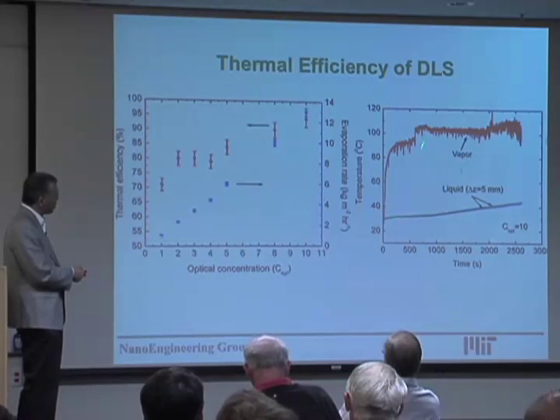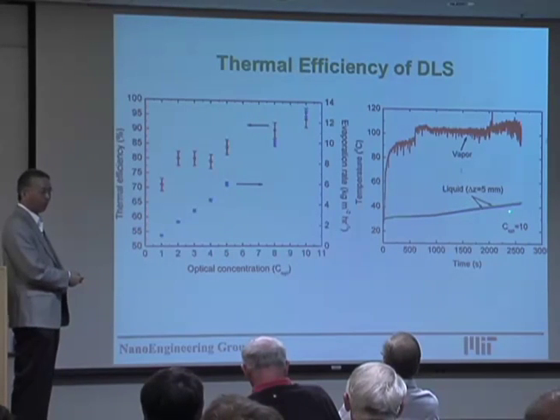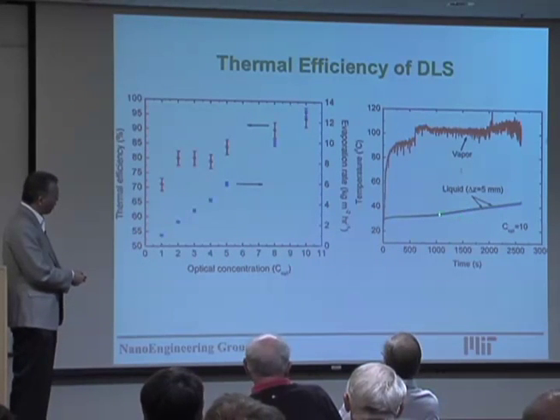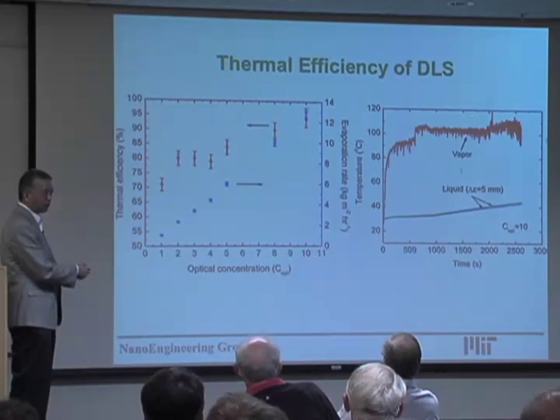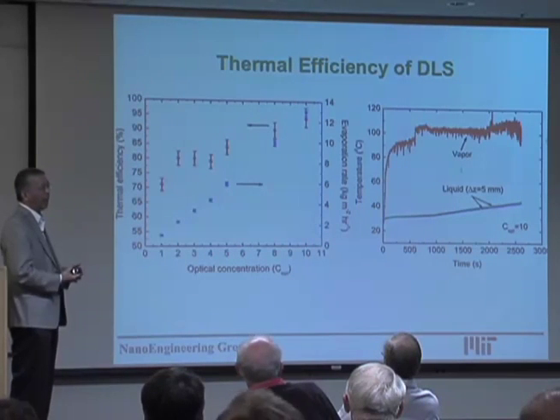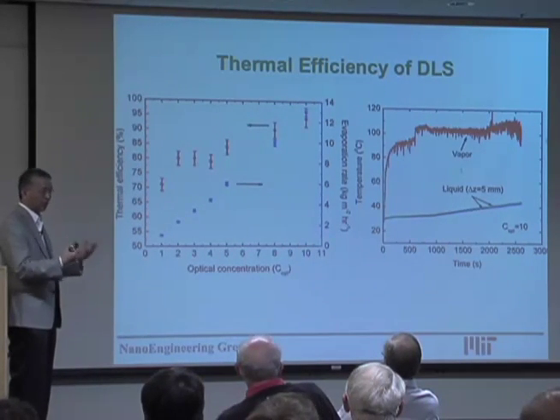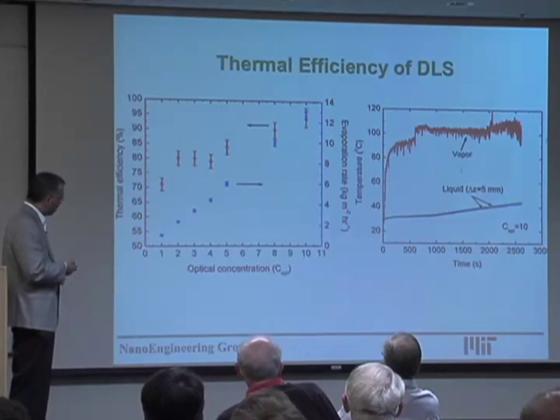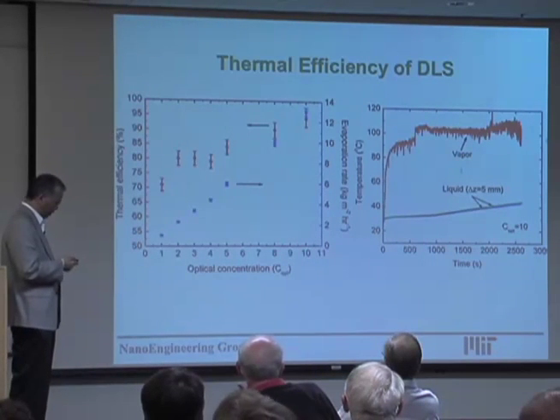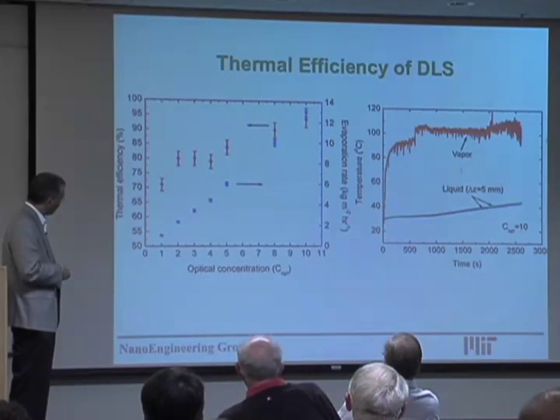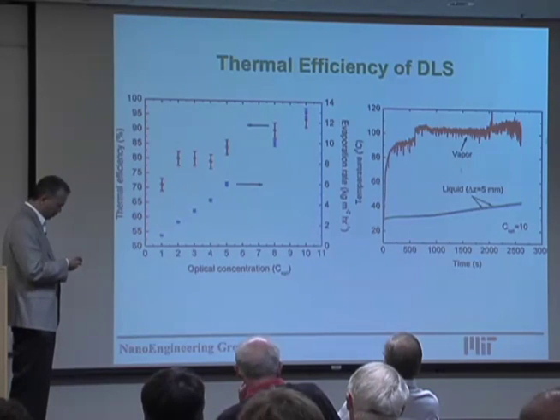What's interesting is the liquid is cold. Here's the water, and here's the vapor, steam. We did this under 1 atmosphere pressure, so the steam is only over 100 degrees. But you can create steam quite effectively using this approach.